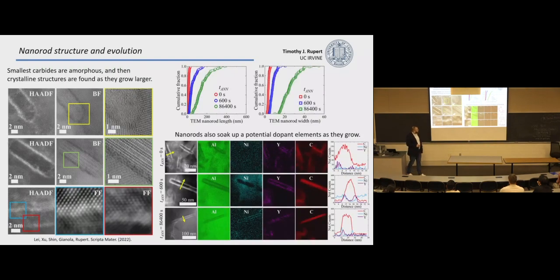When these things are really small, they actually have a disordered structure themselves, kind of like the amorphous grain boundary that they were born at. But as they grow inside of your material, they become crystalline, and you can start to see them take up more and more of the microstructure. There's a lot of details here, but all we're basically looking at is some of the things we add, like nickel and yttrium, which segregate to the grain boundaries, also segregate to interfaces along these carbides that grow in our material.